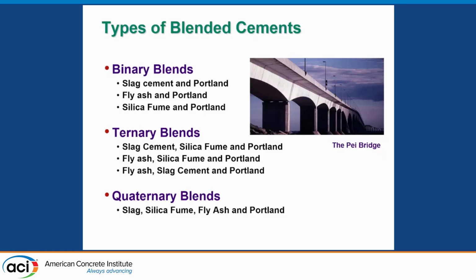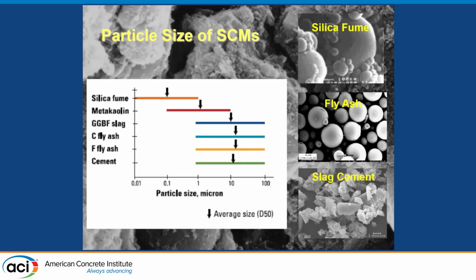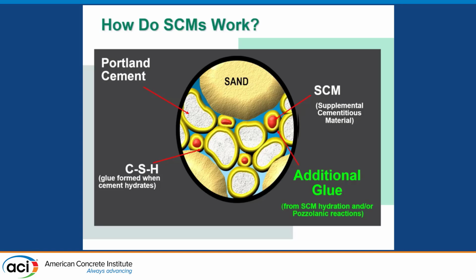So the study that I looked at was looking more at binary blends and ternary blends, and certainly we saw a quad blend on the last presentation. And again, it's managing that particle size and making sure that we're densifying the concrete to our ability to make sure we can extend service lives. And certainly we can see that particle size is a big indicator of how you're going to change the permeability and the tortuosity of those concretes. Certainly most of us know how that pozzolanic reaction works, but for those of you that don't, some of these are making additional glue. Then we have to have the hydroxide reaction, which activates some of our pozzolans. Slag cement is hydraulic in nature, so just add water and we'll get a little strength gain out of it.